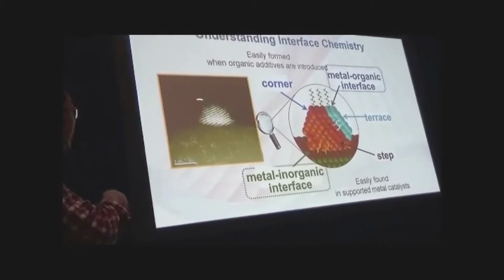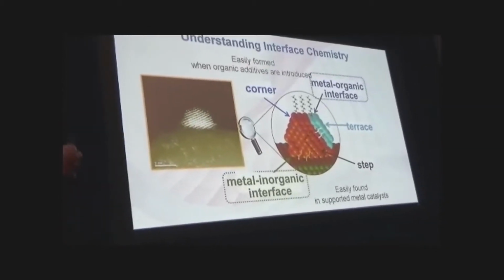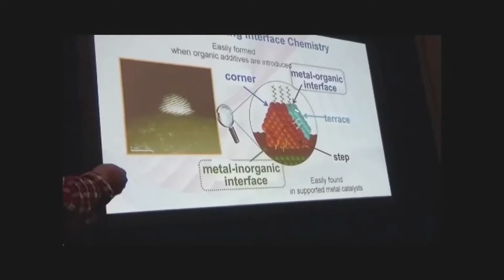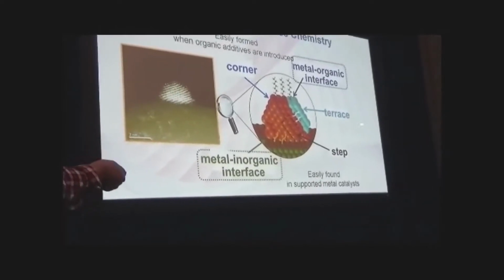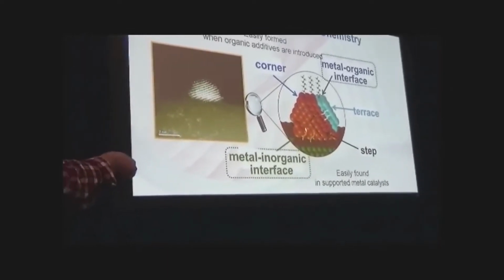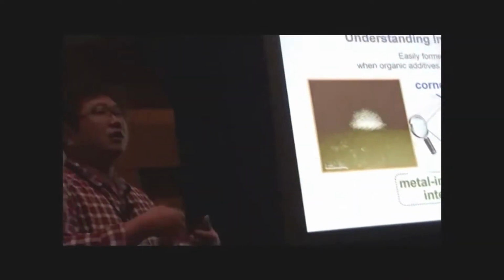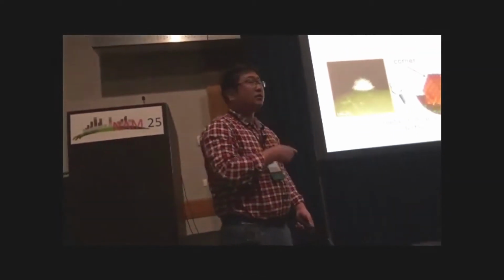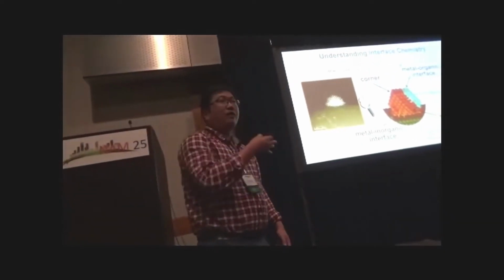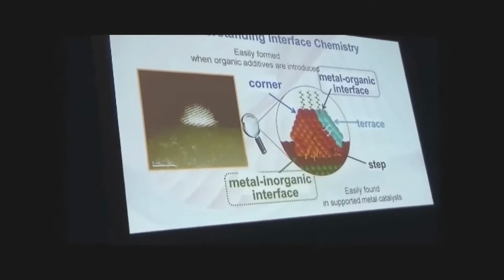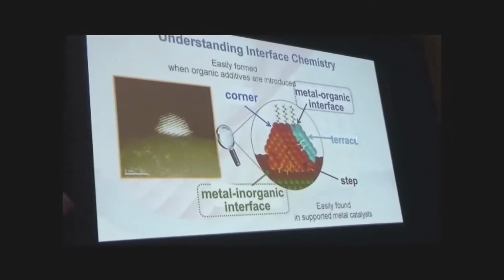As you can see, this is heterogeneous supported catalysis. Heterogeneous catalysis is very complex. Why? There are different exposed phases: terrace sites, step sites, and kink sites. And as the metal particle is usually supported on a metal oxide, that involves the metal-oxide interface here. We also usually introduce organic ligands during the synthesis, so we also have the metal-organic interface here. As Bruce Gates has addressed today, the support can be looked at as a ligand. So the catalytic behavior of the metal particle can be controlled by the coordination environment.